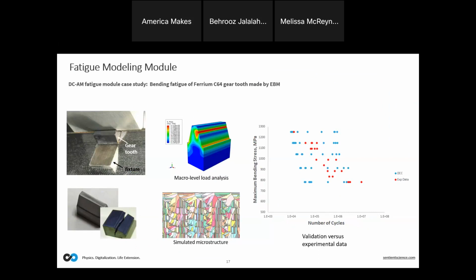I'm trying to answer it in the way that I understand the question. If you're talking about the scatter that we have in the data here, I'm assuming the question is why we have a range of the domains and what's the difference between them. Those domains for the same load level have the same average behavior. That means, for example, if you have 2000 grains there and you plot the grain size distribution, those distributions are of course going to be different for each of those 20 domains. But if you calculate their mean value, it is the same. So their average behavior is the same, their average orientation, their average size is the same. But every single one of those grains, when they are sitting next to each other, is different across those 20 domains.